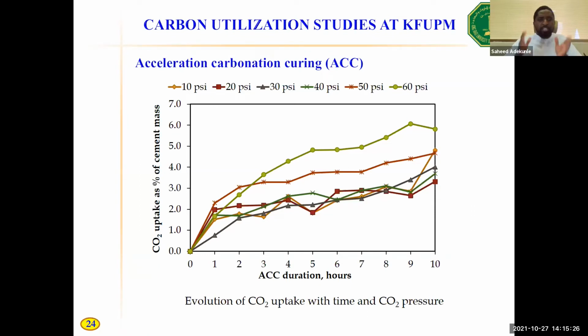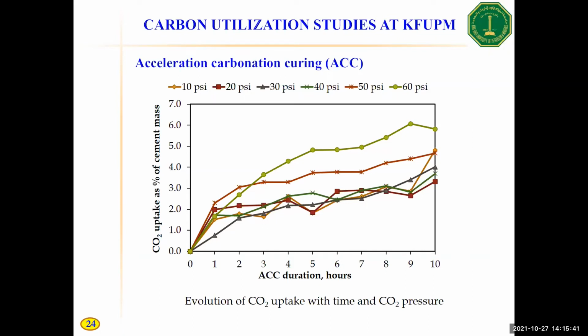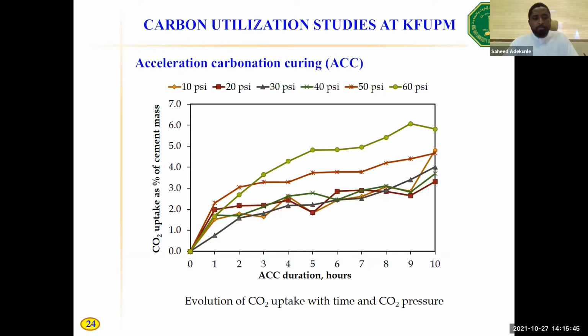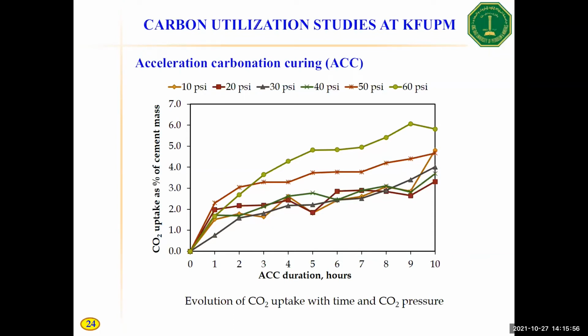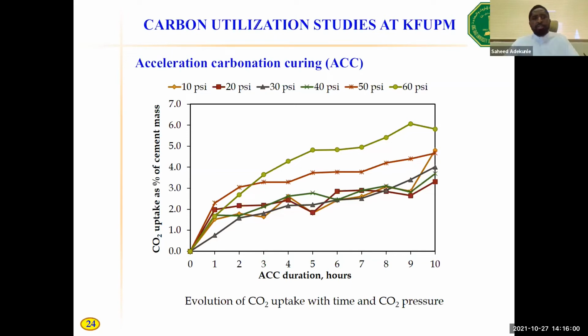As you can see, over a span of 10 hours, we're able to capture 6% by the mass of dry cement in concrete in terms of CO2. For every 1 kg of cement used in this material, we're able to see 60 grams of CO2 captured. This is a good achievement because not only are we able to capture CO2 in this concrete, that capture resulted in accelerated strength enhancement and also enhanced the durability performance of concrete, without affecting the durability performance negatively.